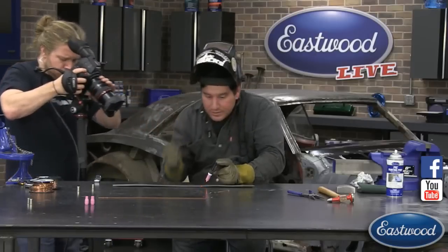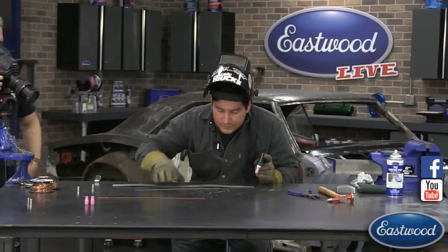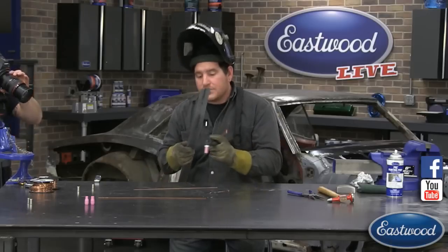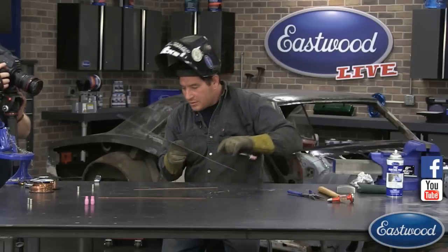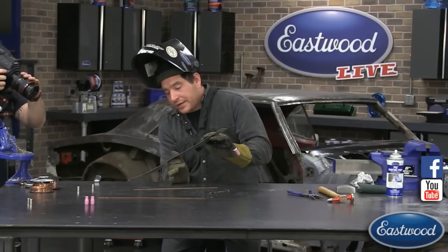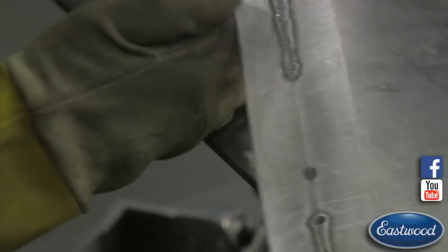So I got to almost max that pedal out to get that filler rod to go into there. I'm actually pumping the pedal to keep it controlled. You can already see it starting to open up on us. So with the 1/16, I can play with the pedal. We're getting penetration, that's for sure. It's almost at the point of blowing through at some of these spots here.